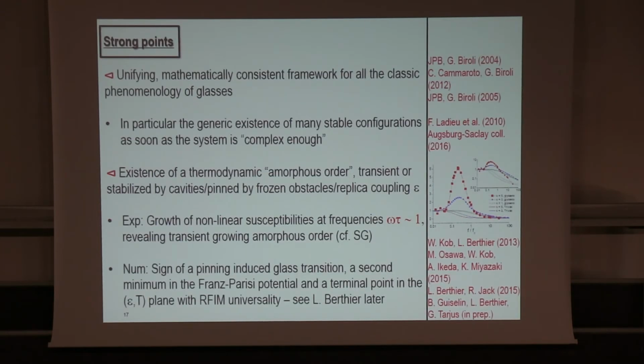Okay, so to conclude, the strong point of RFOT is, as I said, a unifying, mathematically consistent framework for all the classic phenomenology of glasses. In particular, the generic existence of many stable configurations as soon as the system is complex enough. We believe that a glass needs some level of complexity to exist. If the system is too simple, it's never going to get trapped in a rough energy landscape. It suggests the existence of a true thermodynamic amorphous order state, which is transient on the scale of the relaxation time of the system. Beyond this relaxation time, it's of course a liquid, so all this amorphous order unravels and goes away.